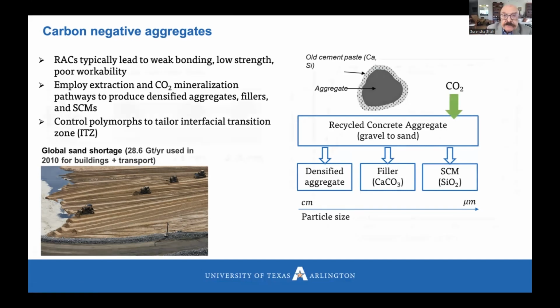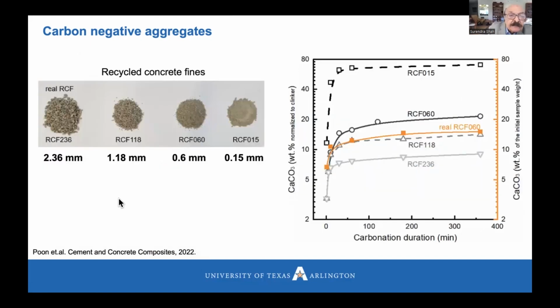the carbon. So here, for example, are the results shown, the work done by Professor Poon in Hong Kong. He carbonated different sizes, and if very fine size, you can see that it can absorb a lot of CO2 because the finer the size, the larger the surface area.